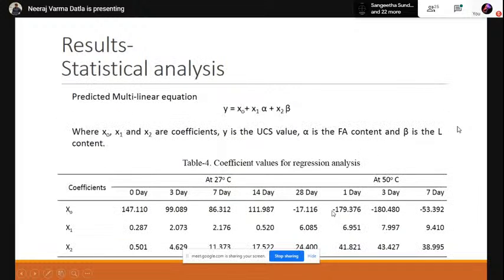And now the last part is the statistical analysis. Here we consider a simple linear equation. Here y is the dependent variable, and alpha and beta are the independent variables, and x0, x1, x2 are the coefficients. Here y is nothing but the compressive strength, alpha is the fly ash content, and beta is the liquid content. After conducting the simple linear regression analysis, these are the coefficients we have obtained. This linear regression analysis was done separately for different curing periods and for different temperatures.